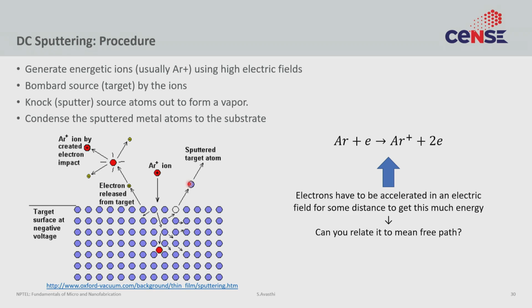So the way it works is that an uncharged argon atom interacts with a very high speed electron, causing it to ionize and then forms two electrons. So it starts with one electron and forms one extra electron. Now, this is in some sense a chain reaction type mechanism, where the emergence of one electron causes an amplification. And so you have several electrons causing cascading ionizations. And ultimately, if this whole thing is above a certain critical size, it would become self-sustaining and plasma.